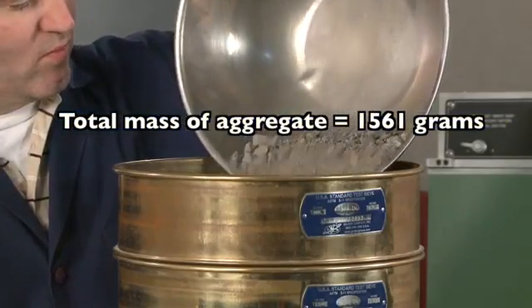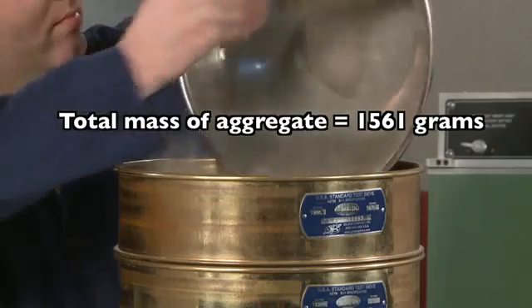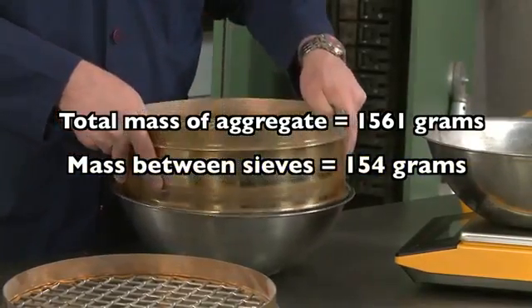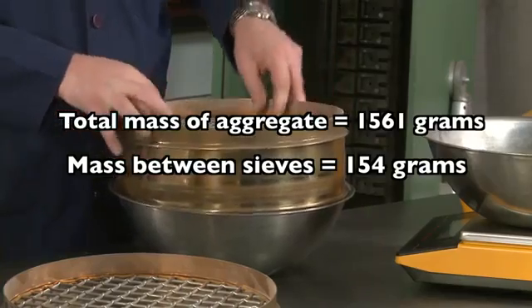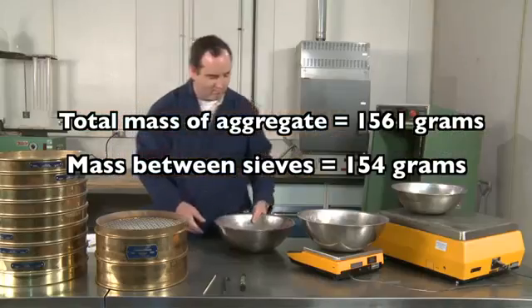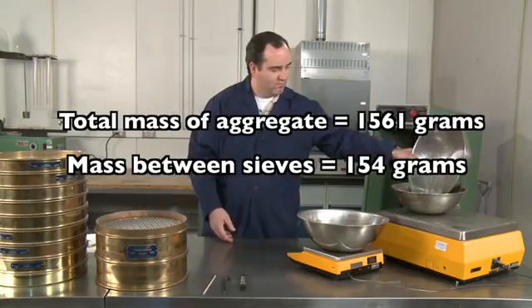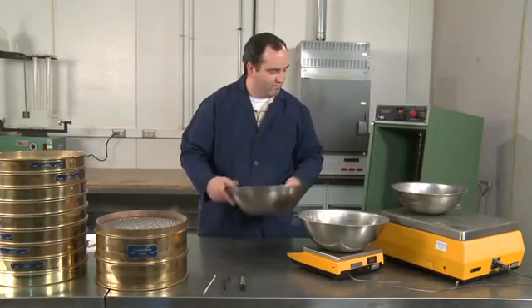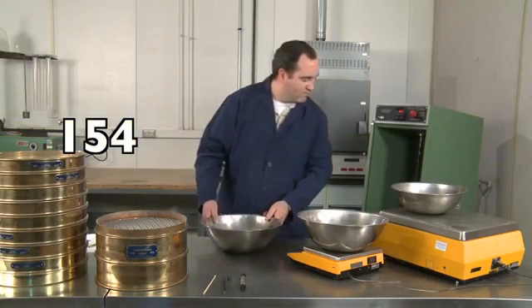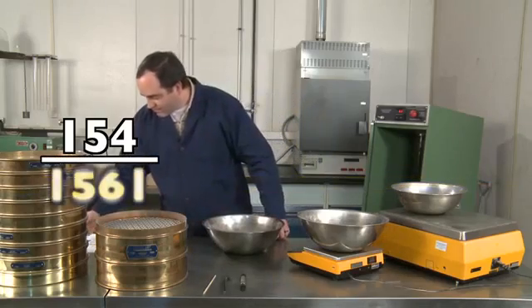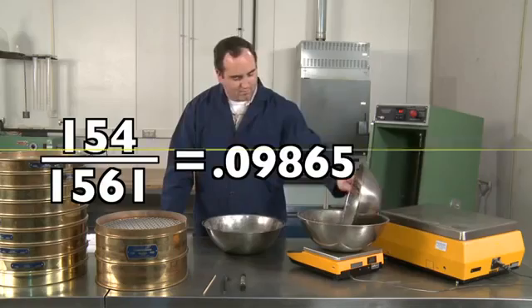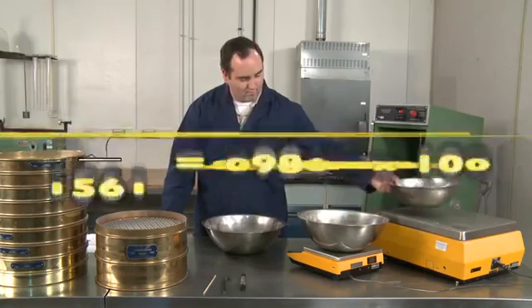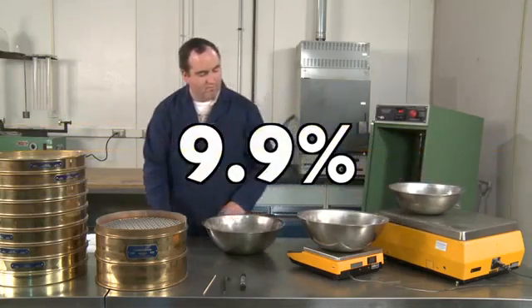For example, if the mass of the extracted aggregate was 1,561 grams, and the mass retained between two consecutive sieves was 154 grams, the percent retained would be calculated as follows. 154 divided by 1561 equals 0.09865 times 100 equals 9.9%.